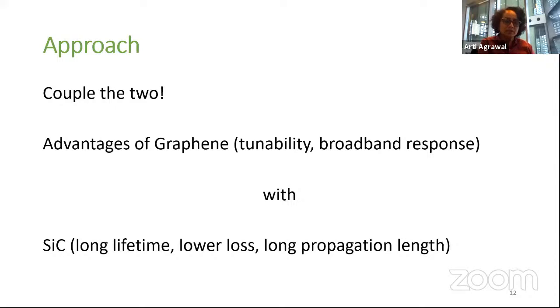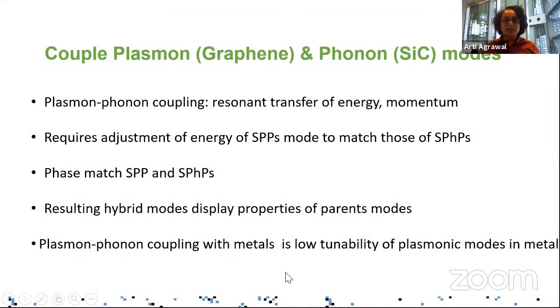Well, what we are suggesting is to couple the advantages of two different material systems, take the advantages of graphene, which is tunability and broadband response, and couple it with the response that we can get from silicon carbide, which is long lifetime, lower loss, and long propagation length. And then together we can form the plasmon in graphene and the phonon in silicon carbide to form what we call a surface plasmon phonon polariton.